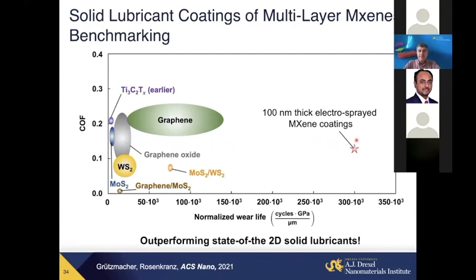But again, keep in mind, there is no reason to believe that titanium carbide Ti3C2 produced by this method is the best MXene. Even for Ti3C2, you can have a variety of different surface terminations, more fluorine, more oxygen, more OH, chlorine, which allow you to control the properties further. However, there are also at least 30 already reported transition metal carbides and nitrides and carbonitrides. And as we discussed earlier, a virtually unlimited number of others possible, and already a couple of dozens of solid solutions have been reported in addition to those stoichiometric ones here.